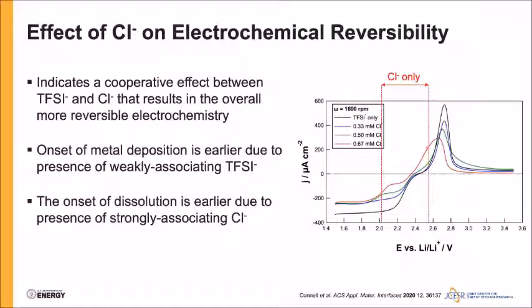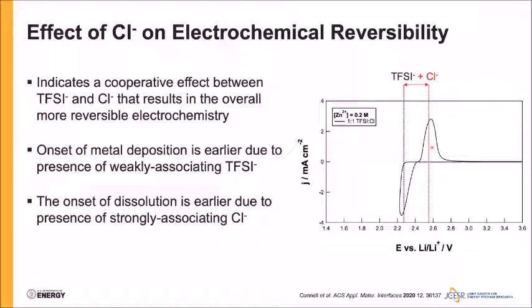This can be rationalized by the fact that chloride relative to TFSI is more strongly associating, and so there's essentially more free energy released by reassociating a zinc cation with a chloride ion in solution. So there's a higher driving force to resolvate zinc into a chloride-rich speciation rather than a TFSI-rich one. If we then sum the contributions, this is what leads to the overall more reversible voltammetry that we see in the bulk plating and stripping behavior. And you really wouldn't have been able to rationalize this if you hadn't gone to the dilute case and been able to pick out the individual contributions of the ions.